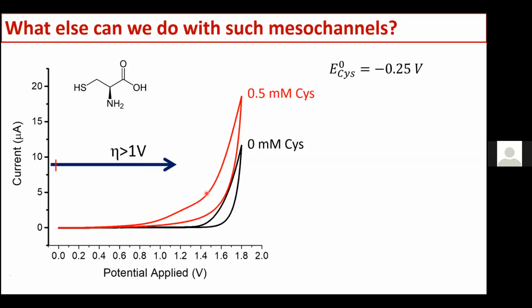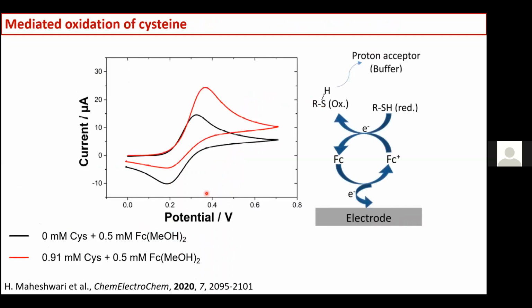So what people generally do is introduce a mediator to oxidize the cysteine, and this way you can lower the overpotential. Here an example is ferrocene. Ferrocene is oxidized at the electrode surface to give ferrocenium, and ferrocenium is reduced by the cysteine, regenerating ferrocene that can be detected again at the electrode surface. And here you can see the cyclic voltammogram of the cysteine in the absence.